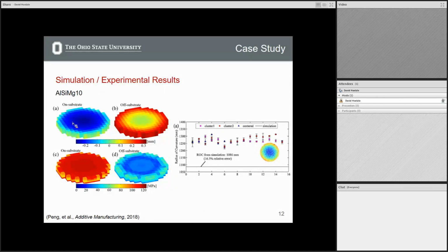This is a heat map. On the top here is a heat map of distortion, and then a heat map of the stress in the part. Right. This is a von Mises stress. This is essentially principal stresses in the part, not giving a direction to it. Okay. So this is also aluminum. I'll go through the case of stainless steel in a second. Nothing too fundamentally different with this, but the main message here is that when it's on the substrate, you get a very little, almost imperceptible deformation because it's being rigidly fixed to the substrate. And then when we release it, you get a pretty large deformation, essentially the effect of it popping off, right?